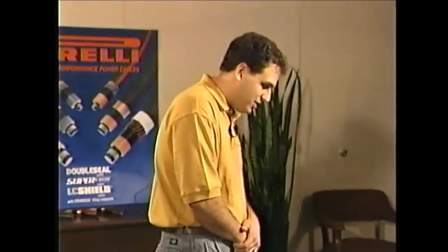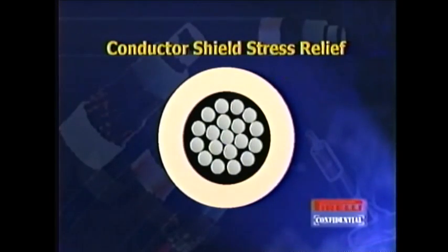So anywhere where you have a potential to have a void in that system, you want to try and avoid it. So one of the ways that you do that, knowing that when you extrude a dielectric material over the conductor, you will not be able to extrude it so that all of the insulating material is in constant contact with the conductor. So you will have gaps. So one of the ways that we avoid having those gaps and having the phenomenon of corona discharge at that very crucial interface is to put a semiconducting conductor shield and extrude it over the conductor so you're filling in all of those voids without an air gap and creating a nice smooth interface.